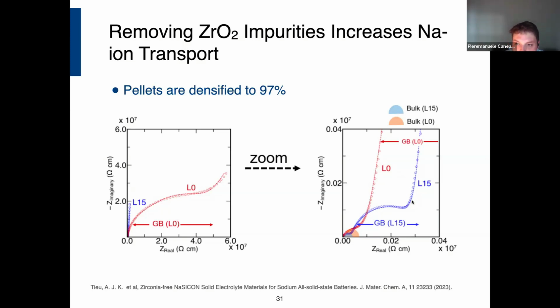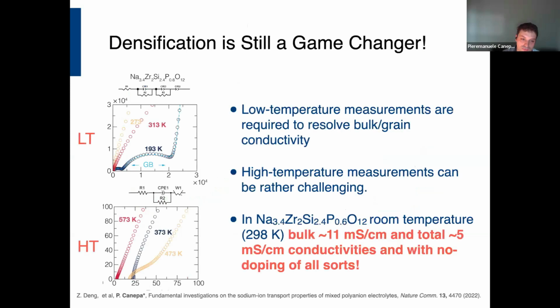I think there is some confusion in this plot. I should not comment on it, but for L0, the grain boundary amount, if you zoom in on the L0 compound, which is the compound with zirconia, is so large that when you zoom in, it becomes basically invisible, and the grain boundary proportion of L15 is significantly reduced. So controlling the zirconia amount in this dense pellet is crucial to ion transport.